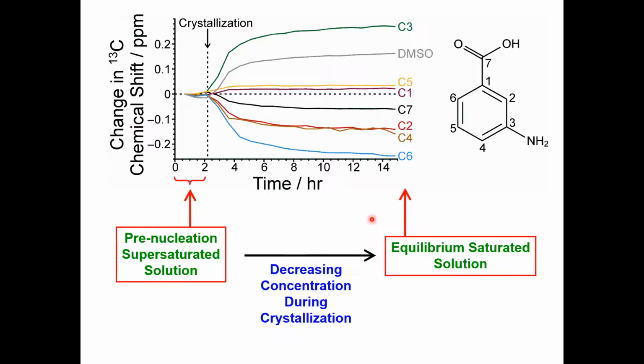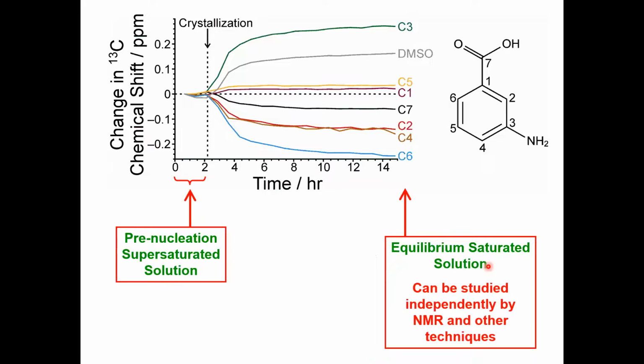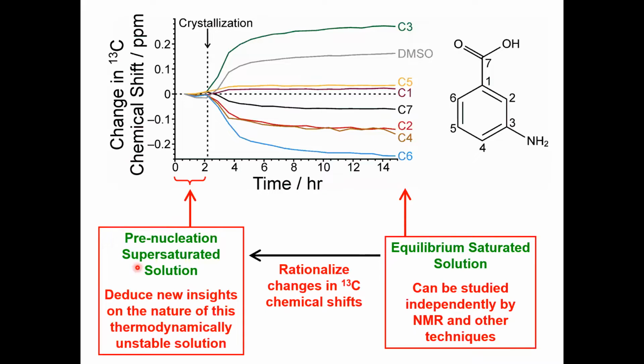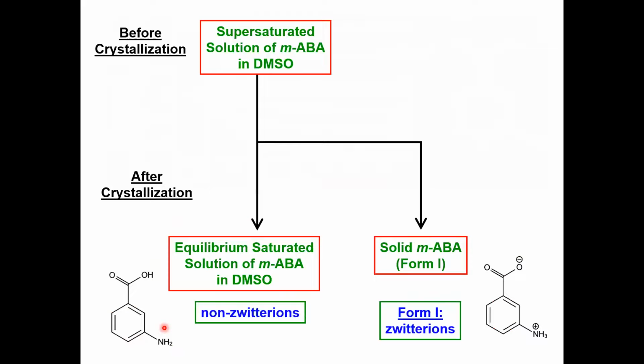So the way we interpret this data is as follows. At the end, we've got an equilibrium saturated solution, and that can be studied independently by NMR and other techniques. So we can get a very complete characterization of that solution. And what we're going to do is rationalize all these changes in carbon chemical shifts, looking backwards in time to give us insights into the nature of this thermodynamically unstable solution before nucleation actually happens. And here's just a very, very brief summary of the conclusions from this type of analysis.